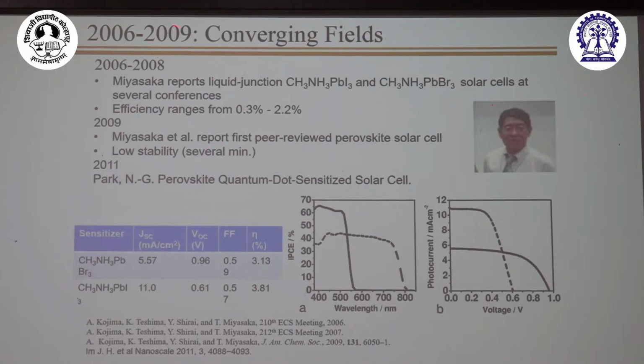And then in 2006 to 2009, converging fields, right? So Tsutomu Miyasaka made a liquid junction solar cell with methyl ammonium lead iodide and bromide. And he had published at conferences. Nobody paid attention because you got a couple of milliamps. That's his data here, you can see here. And it did not last. Within 5 minutes, it was dead, right? Because it corroded in the solvent when you shine the light. So that was the first solar cell, the JACS paper he published. And at the same time, Nam-Gyu Park also published, and he called it a perovskite quantum dot sensitized solar cell. So it was just evolving. Again, both were liquid junction solar cells at the time.